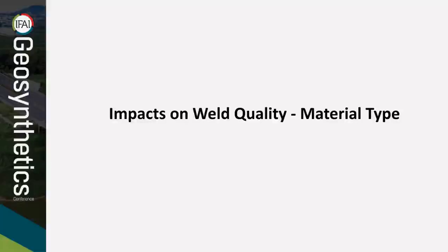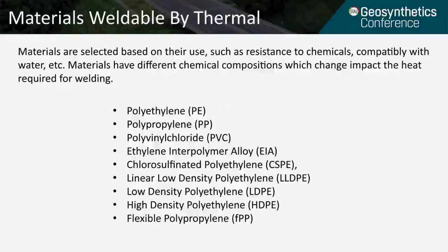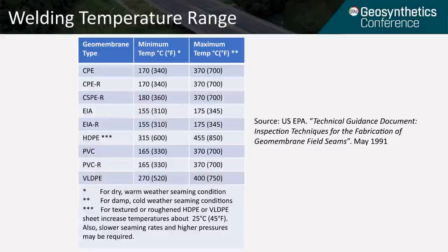In this section, we're going to look at how material type can impact weld quality. Designers are going to choose the material used on a project based on resistance to chemicals, compatibility with water, resistance to stress, reinforcement, etc. These materials will have different chemical compositions, which ultimately change the requirements for welding. This table shows the minimum and maximum welding temperature range for different geomembrane formulations. For example, if you look at HDPE, its range is 600 degrees to 850 degrees Fahrenheit, whereas the next line, PVC, is 330 degrees to 700 degrees Fahrenheit.